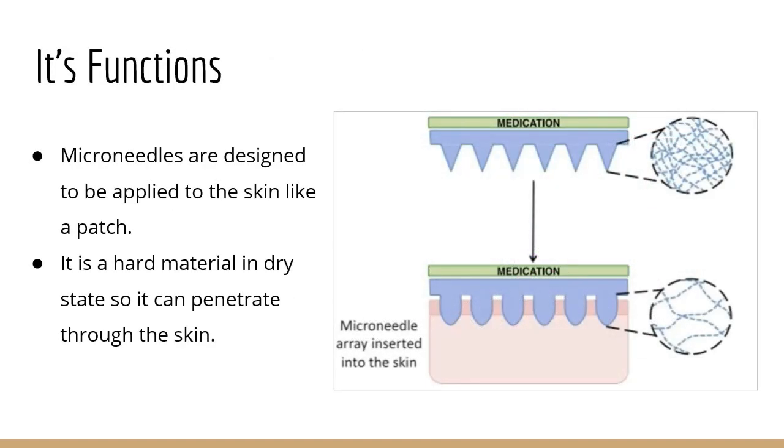How it works. Microneedles are designed to be applied to the skin like a patch. The medication is stored adjacent to the microneedles. It is a hard material in dry state so it can penetrate through the skin. When the patch is pressed onto the skin surface, the needles are able to cross the outermost layer of the skin and the fluid from the skin results in swelling of the needle and forms a jelly-like material.